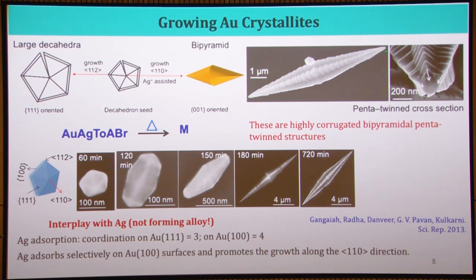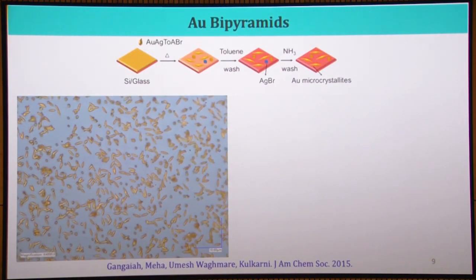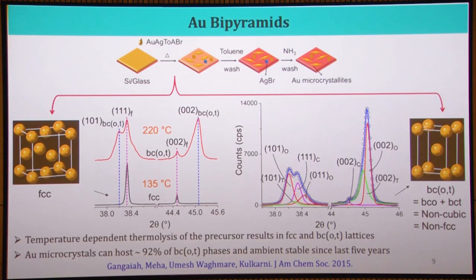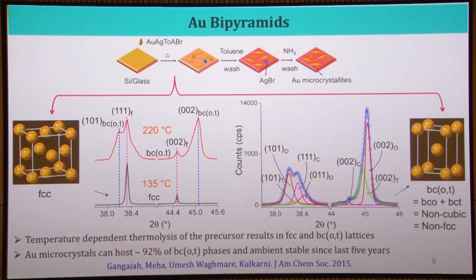We can grow such crystals maintaining the pentagonal geometry into around 10-micron-length microcrystals. They are visible using a good optical microscope — all rice-like structures. We call them gold rice: nice linear structures, all looking like rice under the microscope. Temperature and various conditions play a big role — it's a magic recipe; only then will you end up with these kinds of structures. Having done that, we scanned the entire phase space, varying concentrations, relative ion concentrations, solvent medium, substrate, temperature, and more. One example that led to very interesting results concerns the thermodynamic parameter — temperature.